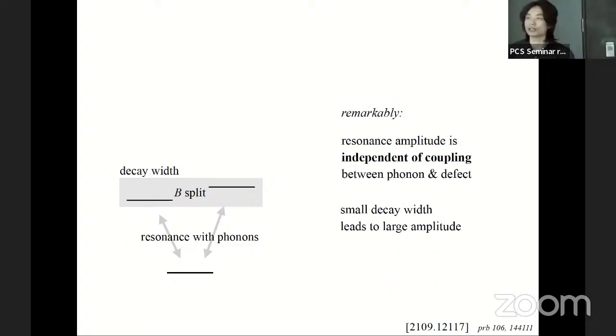And remarkably, we can show that the resonance skew scattering amplitude is, for a range of parameters, independent of the coupling to the leading order. So that's a feature of resonance. Resonance means it doesn't really depend too much on how much you drive it. Right. So it's independent of the coupling, which makes it very large. And moreover, as long as the decay width is larger than the split, the smaller the decay width is, the larger the amplitude will be.